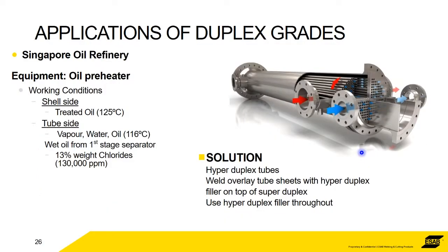This is a nice application that we had in Singapore in an oil refinery, whereby the working conditions were at 125 degrees, but it had 13% chlorides. So in terms of corrosivity, it's a nasty corrosive solution, and it's at temperature. Initially, the designers were thinking that they'd have to use something like an Inconel alloy 625, a nickel alloy, which is obviously going to be hilariously expensive. So the solution, found by trials and testing, was to use hyperduplex.